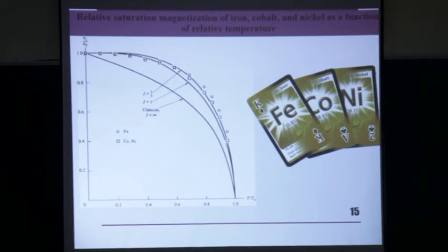That's why in the previous lecture I was emphasizing J equal to half, because I know that it's going to come up in this case. Okay, so what this means is, it is definitely better to use the quantum theory in the case of ferromagnetism, because although this is not completely off, it's not terrible, but it's not that good either. So you can see that the quantum theory fits better with the experimental data.